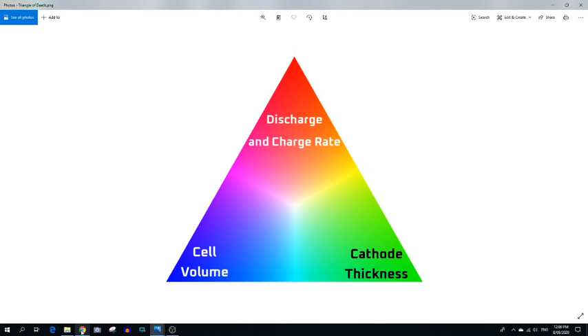So one of the limiting factors for batteries is the competition between discharge and charge rate, cathode thickness, and cell volume. You can't do all of those things at the same time. If you crank the discharge and charge rate up too high, it creates too much heat. If you make the cathode too thick, it creates too much heat. And if you create a cell that's too large, that creates too much heat.